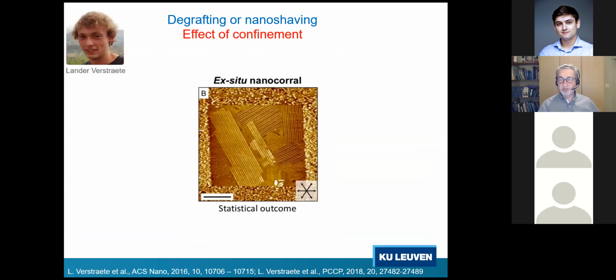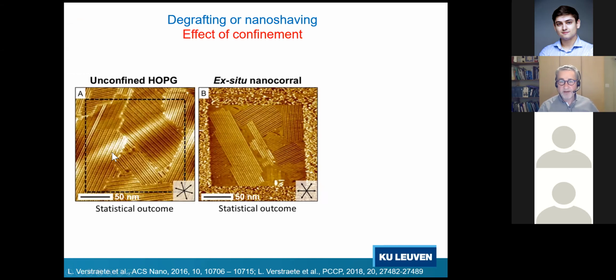Well, the PhD student who did all of this was pretty excited initially, but he turned quite disappointed quite quickly, because these are domains of that molecule that I had introduced before into a square corral. You see different domains, but if you compare this with graphite, which happened on pristine graphite, there is almost no difference. So there seems to be no effect of the confinement, because we had hoped that by putting molecules in small 2D containers, that would affect their self-assembly properties.